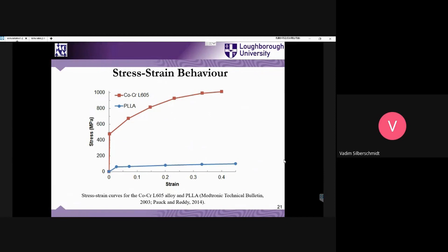As I've already mentioned, metallic materials being so stiff, there is a desire to find materials with properties closer to those of biological tissue, so that the property mismatch would be smaller. As presented earlier in the lecture, polymers are an obvious choice because they are significantly softer than metals. Here you can see the stress-strain curve for cobalt-chromium alloy versus PLLA, and you can see a significant difference in their performance.